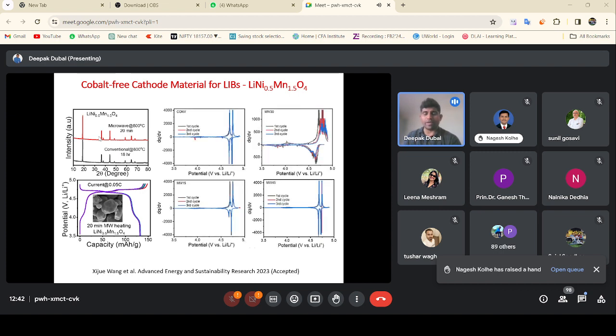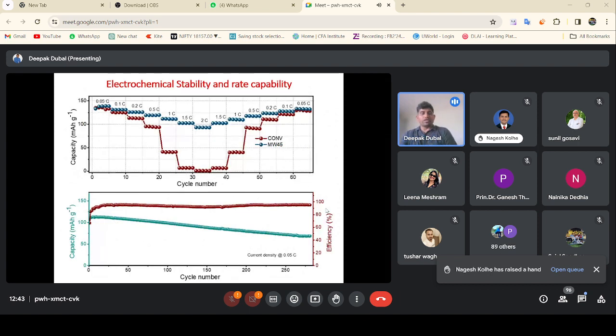And we also tried to explore the mechanism, because in the X-ray diffraction, we didn't see much difference. But when we did the electrochemical testing, you can clearly see that the electrochemical signature of microwave synthesized material at different times is different. You can see the conventional and then the material synthesized with microwave at 45 minutes have a similar signature. So this means we need at least 45 minutes to synthesize this cobalt-free cathode material using the microwave synthesis. So we also tried the electrochemical stability and rate performance.